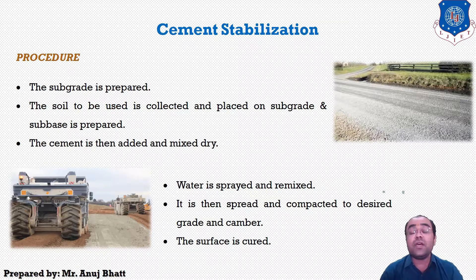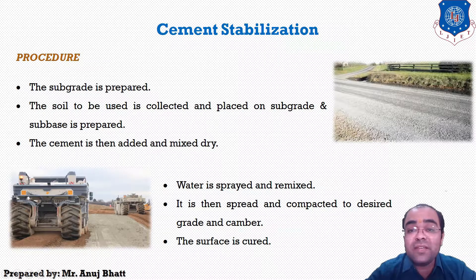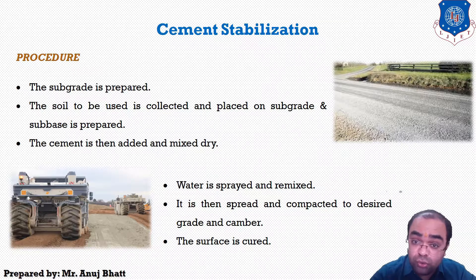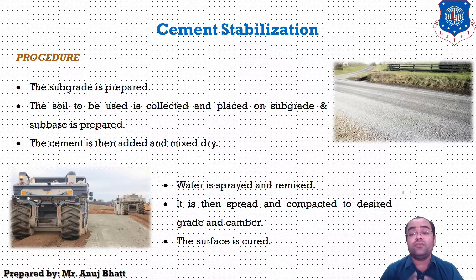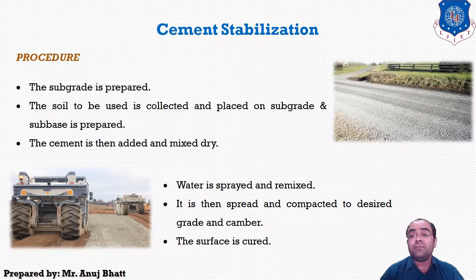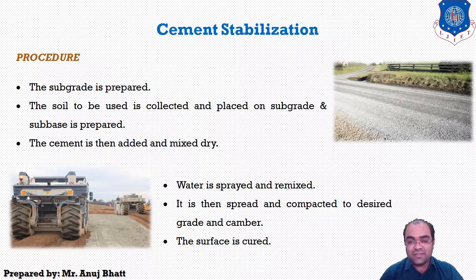Soil cement mixtures are also used to provide wave protection on earth dams. Well-graded soil containing gravel, coarse sand, and fine sand will require 5 percent of cement by weight. Plastic clays require 14 percent of cement by weight. For better pulverization and degree of mixing, there is an optimum moisture content corresponding to the maximum dry density or strength of the soil cement mix.